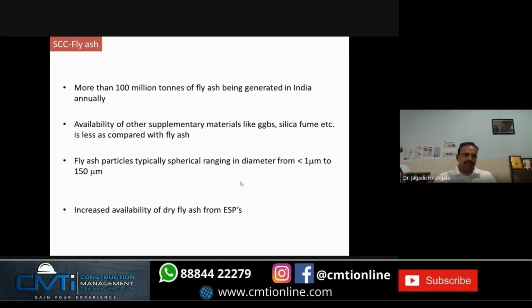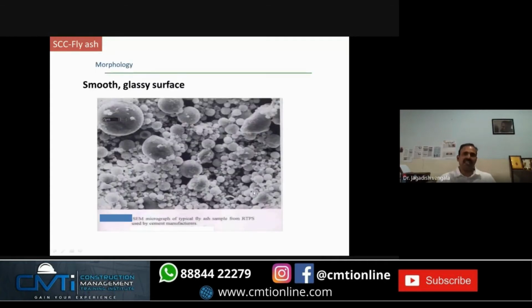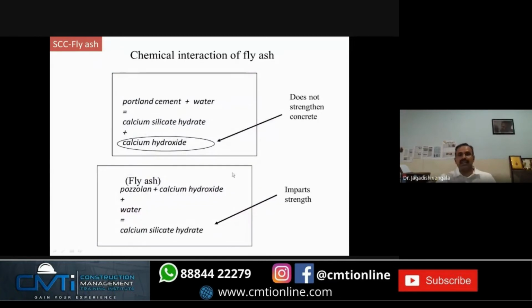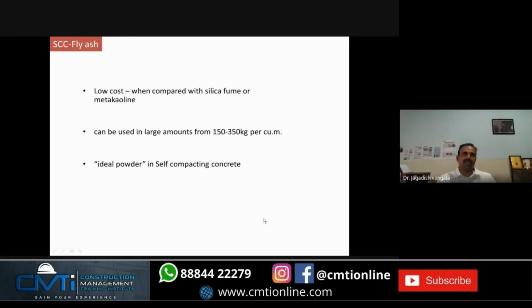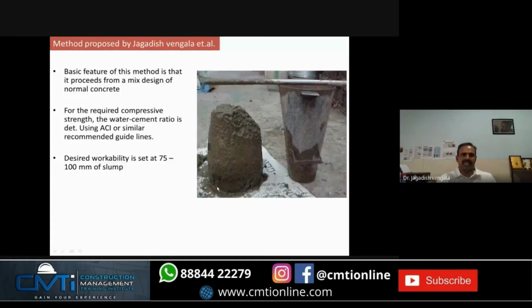So now I'll take up one more: how do you make SCC using fly ash as the cementitious material? We know that a large amount of fly ash is being generated from our thermal power plants, and the fly ash particles are spherical in nature with a smooth, glassy surface, and it gives the ball bearing effect. The excess calcium hydroxide, if you add fly ash, will create more calcium silicate hydrate, which adds strength to the concrete. And unlike silica fume or metakaolin, you can add it in larger amounts because heat of hydration won't be there, up to 150 to 350. That's why we call it the ideal powder in SCC.